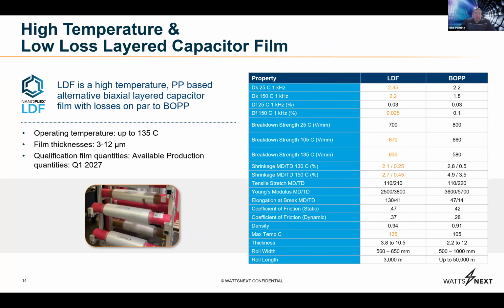There you go. So LDF. LDF was the other flavor of nanoplex we're talking about, the low dielectric loss. Here I'm comparing it in a table, hard numbers against BOPP. LDF is a little different than the previous version of nanoplex we talked about. The dielectric constant is similar to BOPP. It's a little higher, about 10% higher, 2.35 to 2.2 for BOPP. Dielectric loss is nearly identical, so it's got the really low DF, the loss there. Breakdown strength is right on par.